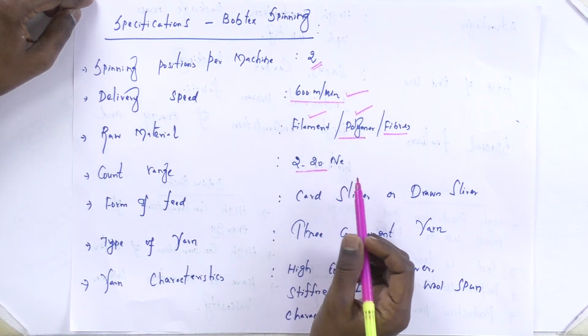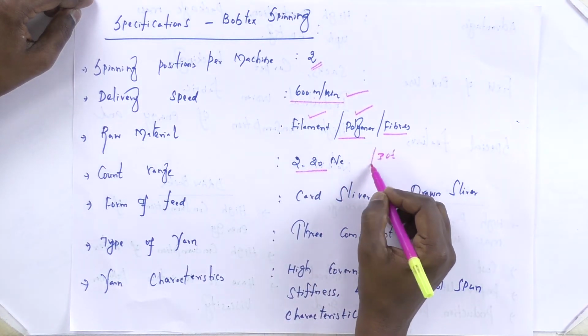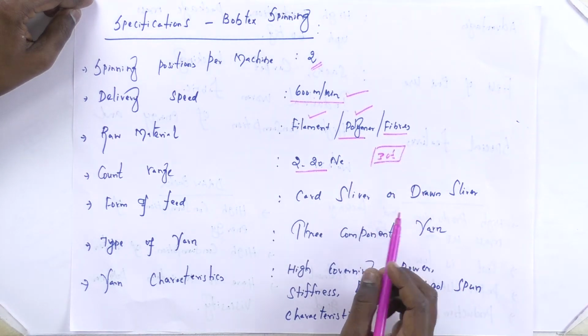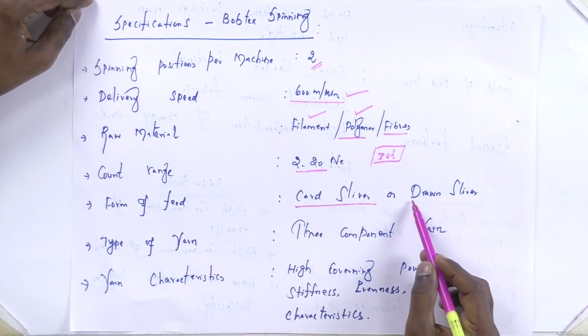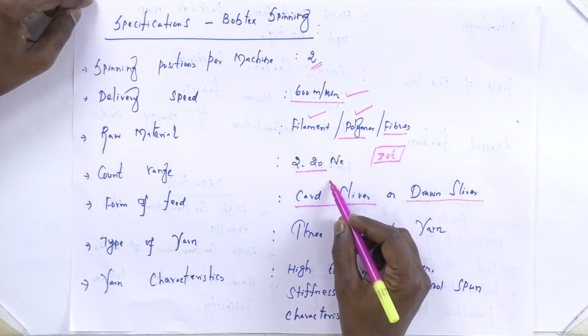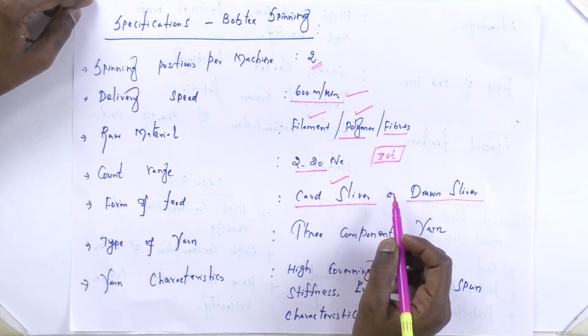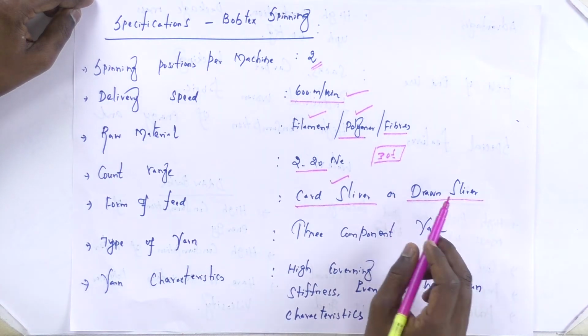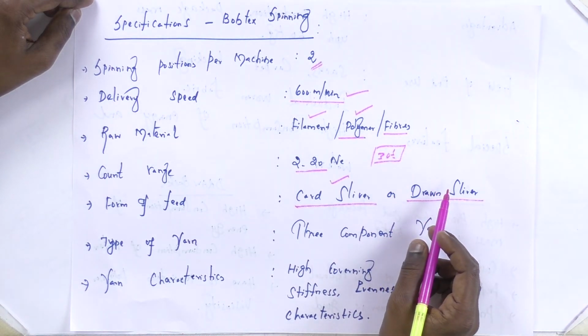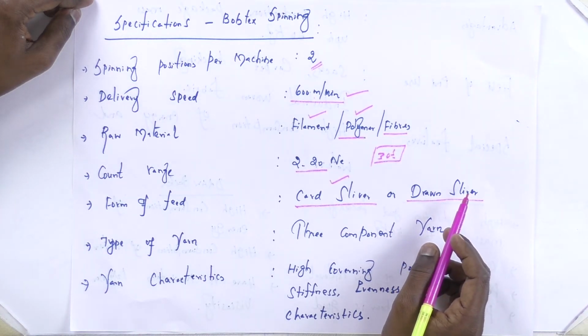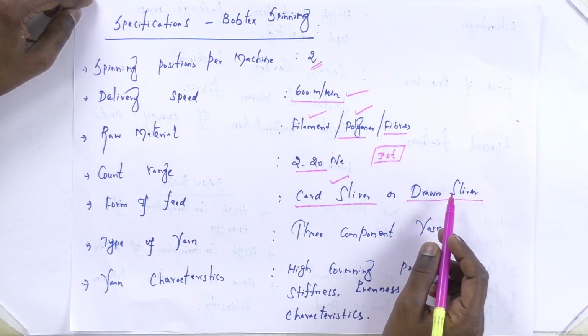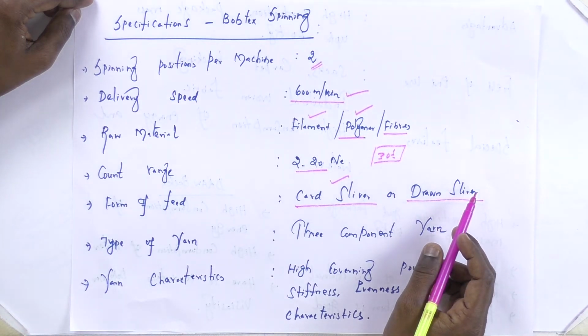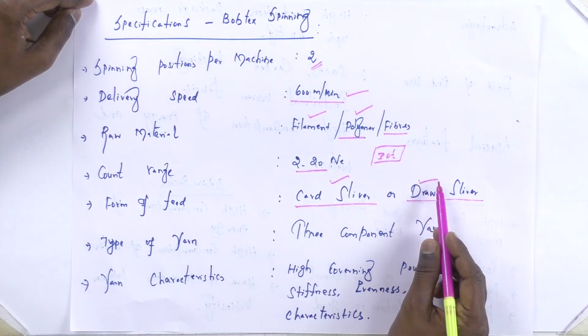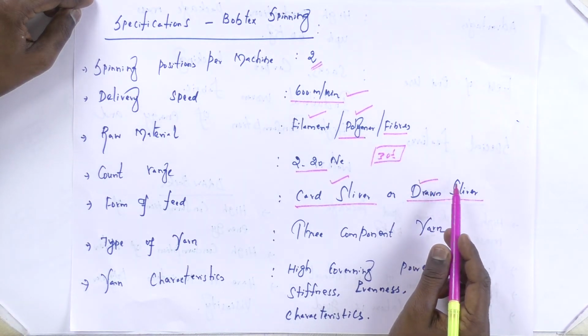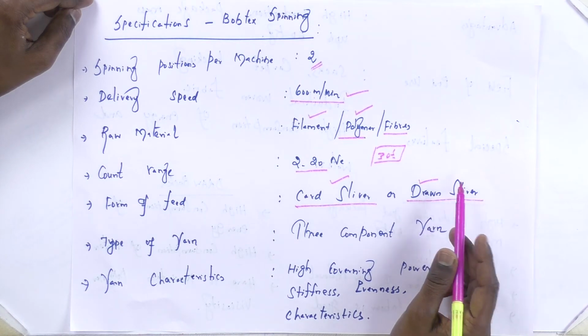In case of rotor spinning, we can go up to 30 count. Here maximum we are using 80 count range. The form of it may be card sliver or drawn sliver. The card sliver is enough for producing the Bobtex spinning yarn, but if you want more quality of fibers in its surface, then we can use drawn sliver. Drawn sliver consists of uniform fibers, more uniform when compared to card sliver. So the drawn sliver is best suited for producing good quality Bobtex spinning yarn.